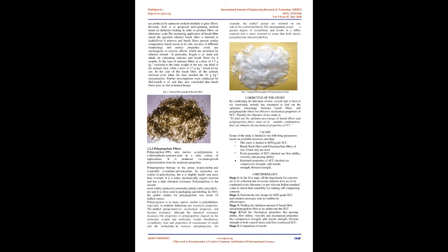Several studies have shown that fiber-reinforced composites are more efficient than other types of composites. The main purpose of the fiber is to control cracking and to increase the fracture toughness of the brittle matrix through bridging action during both micro and macro cracking of the matrix. Debonding, sliding, and pulling out of the fibers are the local mechanisms that control the bridging action. In the beginning of macro cracking, bridging action of fibers prevents and controls the opening and growth of cracks. This mechanism increases the demand of energy for the crack to propagate. The linear elastic behavior of the matrix is not affected significantly for low volumetric fiber fractions.